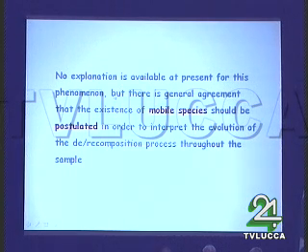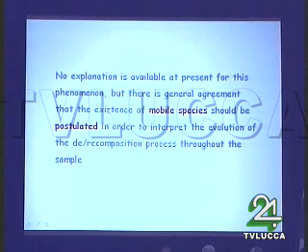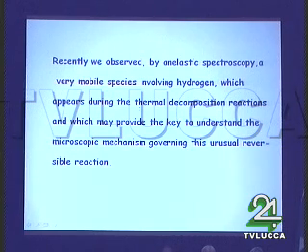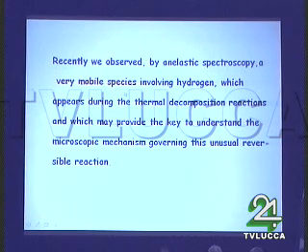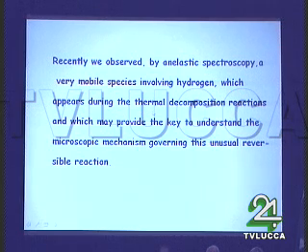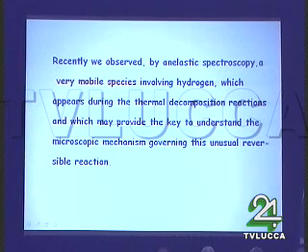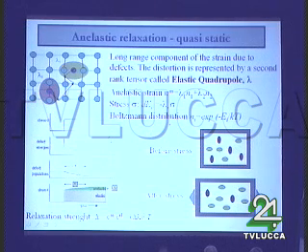But there is a general agreement that the existence of mobile species should be postulated in order to interpret the evolution of the de- and recomposition process throughout the sample. Recently, we observed by anelastic spectroscopy a very mobile species involving hydrogen, which appears during the thermal decomposition reactions and which may provide the key to understand the microscopic mechanism governing this unusual reversible reaction.